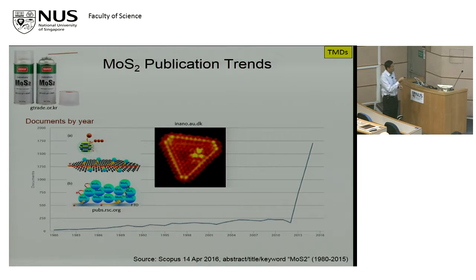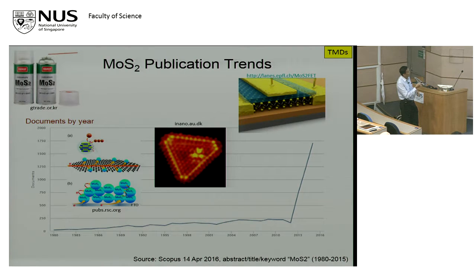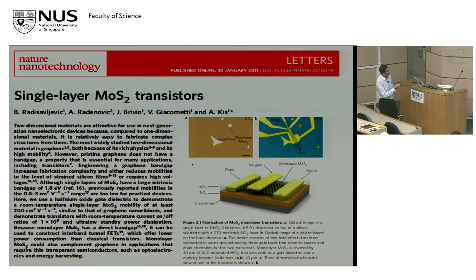where this is the Besenbacher group in Denmark that showed a 2D image of a several-layer-thick MoS2 island, okay, in the 90s. But really, I believe it was this paper by EPFL in 2011, where they made a transistor out of single-layer MoS2 that caused this sudden increase, okay? And basically, this is the paper, Andras Kis's, basically using a single-layer MoS2, because it has a band gap, you don't have the problems of graphene where you can't turn it off. You can turn it on and off now. But of course, MoS2 has lower mobility. It is harder to prepare, and there are other issues, growth issues and all that people are still working on. But in principle, you can make a 2D device that's very small, using only one layer of material because it has a natural band gap.